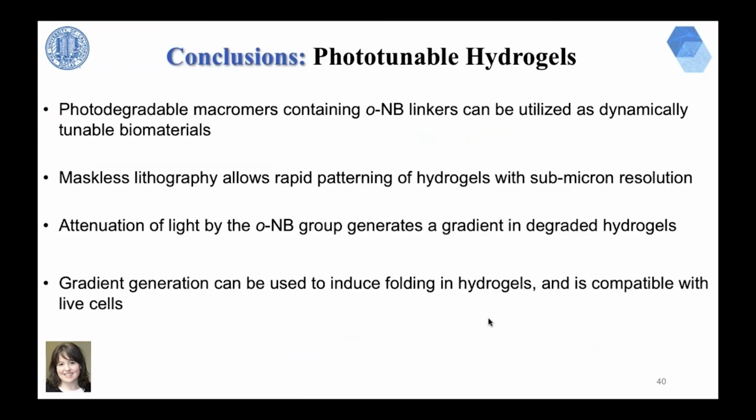So this brings me to the conclusions for this presentation. We've shown that photodegradable macromers containing o-nitrobenzyl linkers can be utilized as dynamically tunable biomaterials. Using maskless lithography allows rapid patterning of hydrogels with submicron resolution and the generation of many replicates within a single system. Attenuation of light by the o-nitrobenzyl group generates a gradient in degraded hydrogels, and that gradient generation can be used to induce folding in our hydrogels in ways that are compatible with live cells.